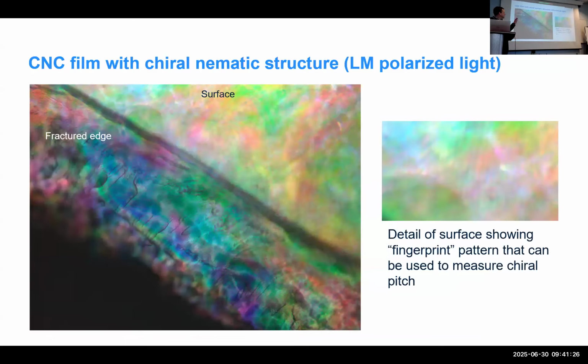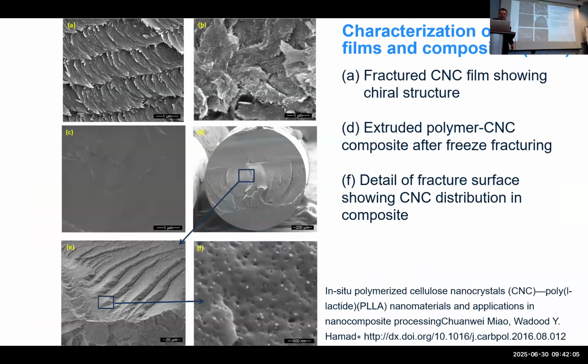You can image sheets of cellulose nanocrystal films with polarized light. And you get all kinds of information, including measuring the fingerprint pattern, which tells you the chiral pitch of that chiral nematic structure. As you go through the film layer by layer, it's changing a little bit until it goes through one complete rotation in terms of orientation of those cellulose crystallites. And that's what makes CNC films iridescent, like a butterfly wing. So, all kinds of interesting things.